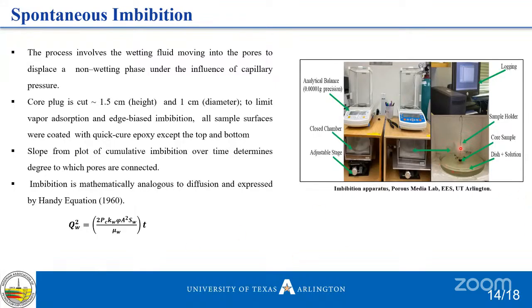So what we now did was to suspend this sample from a high resolution balance. What I mean by high resolution balance is that this can measure up to 5 decimal units, like 0.00000. The sample is suspended from a high resolution balance with the bottom of the sample just contacting the liquid solution. Once it touches the fluid, you start the imbibition and you start logging. A typical process is to log the first 2 minutes. It's going to rise fast the first 2 minutes because of adhesion and the meniscus around the sample. And then every 30 seconds for the next 2 hours, and then you can proceed to 2-minute intervals. That is what we use for the processing.